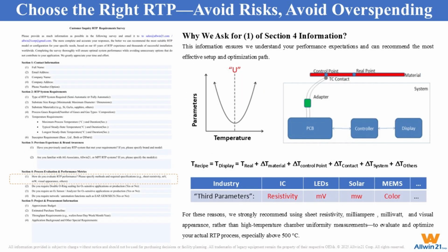This RTP evaluation methods information ensures we understand your performance expectations and can recommend the most effective setup and optimization path. Based on our experience supporting more than 1,000 RTP installations across 40-plus countries, we have found that many users initially evaluate RTP only by temperature uniformity. After further discussion, most customers adopt more practical and meaningful metrics, such as sheet resistivity, milliampere, milliwatt, and visual inspection, often achieving significant improvements in process stability, cycle time, temperature requirements, and even equipment lifetime. Simple methods such as a U-shaped process evaluation curve can quickly guide recipe optimization.